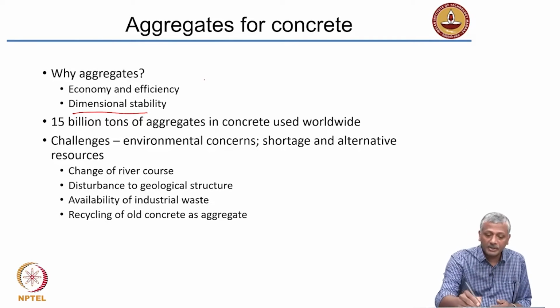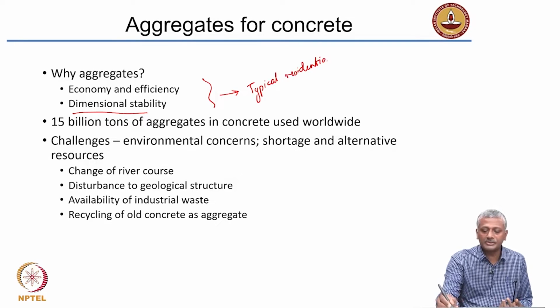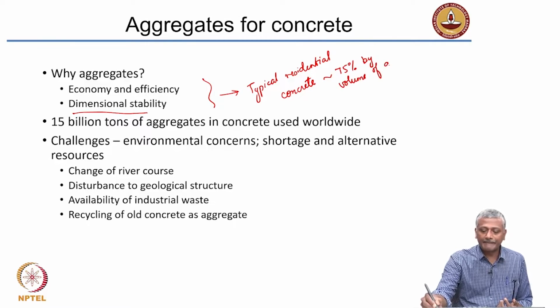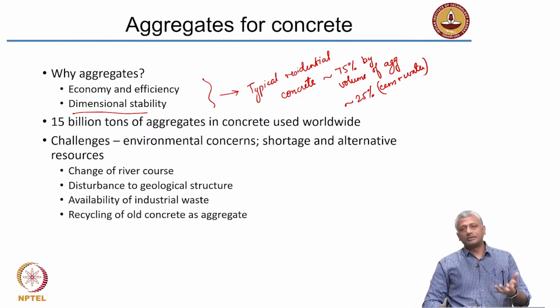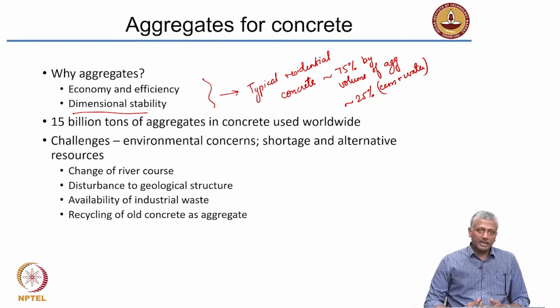So, if you actually look at typical concrete, let's say residential concrete, the concrete that is typically used for building houses, typical residential concrete will have nearly 75% by volume of aggregate. That means only 25% is cement plus water. So, a large fraction of your residential concrete, low grade concrete, will typically be aggregate. And that's because such concretes are typically low grade, low strength, and they'll have a lot of problems with shrinkage. So, more aggregate will prevent large amounts of drying shrinkage from happening. Okay, so aggregates are absolutely essential, otherwise the concrete will become very difficult to manage with respect to dimensions or with respect to the cost.